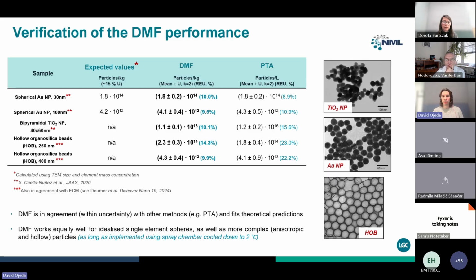In the table, in the column in the middle, we can see the results obtained by the DMF, which we were checking against an orthogonal technique, in this case particle tracking analysis, on the right-hand side. And we saw that for all the materials tested, the performance of the method was quite satisfactory.